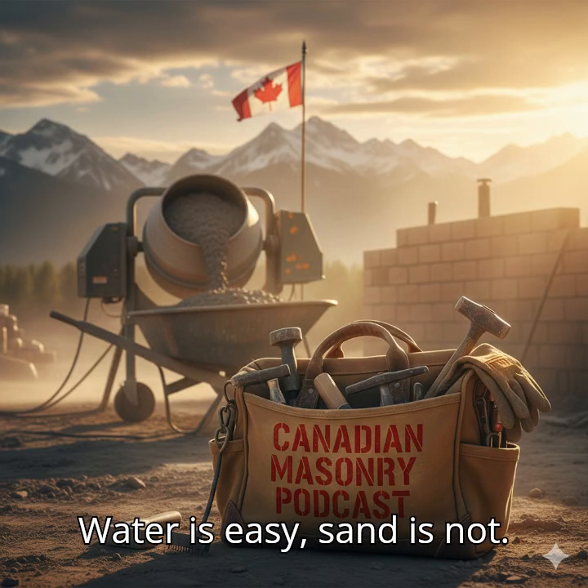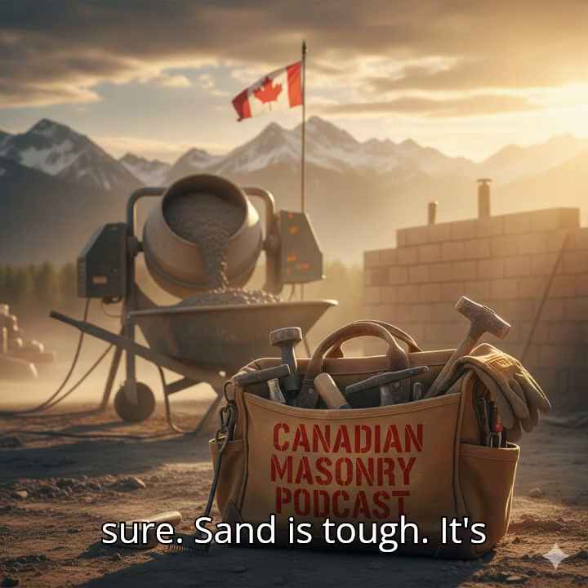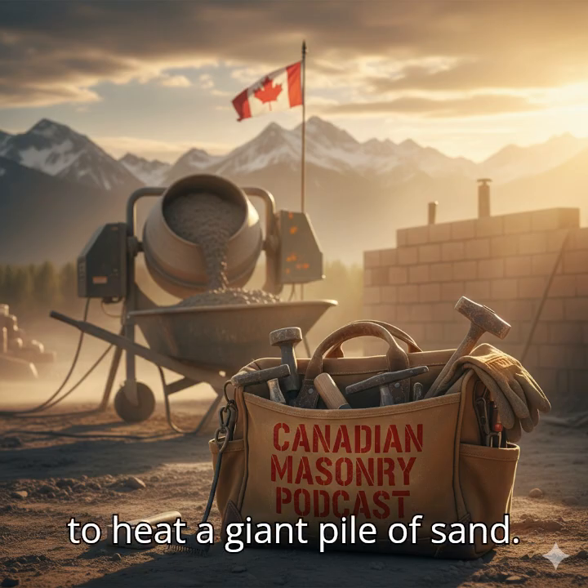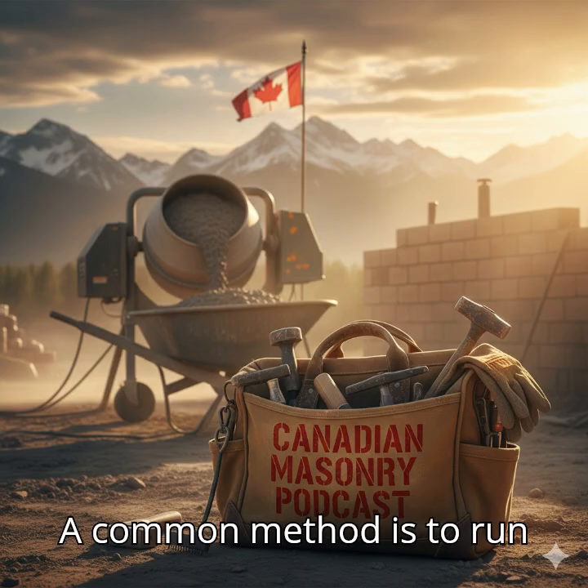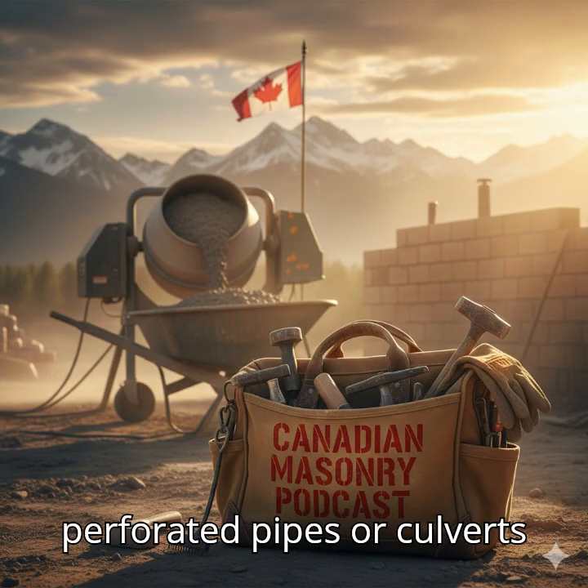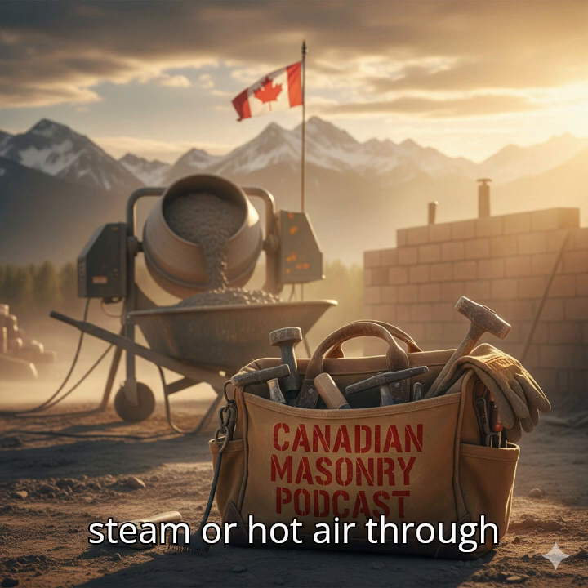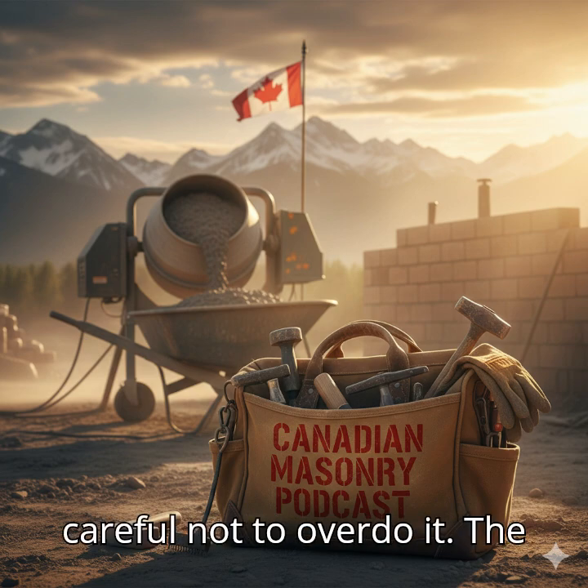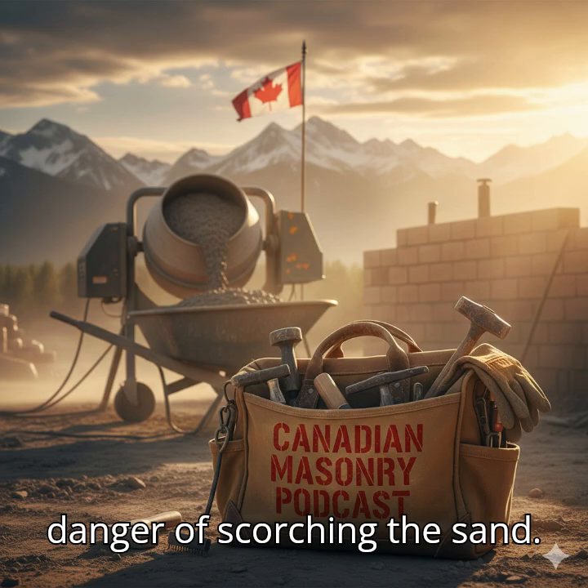Water's easy, sand is not. Water is the easiest, for sure. Sand is tough. It's labor-intensive and expensive to heat a giant pile of sand. A common method is to run perforated pipes or culverts under the pile and circulate steam or hot air through them. But you have to be careful not to overdo it. The danger of scorching the sand.